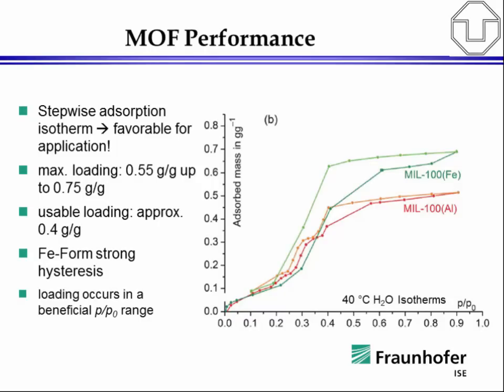Here it is really the tunability. Metal organic frameworks can be tuned in terms of hydrophobicity, hydrophilicity, that is the water uptake and at which relative humidity the water uptake starts can be tuned. And you can see this here for an aluminum-based MIL and for an iron-based MIL. They have both very high adsorbed mass and water uptake, here almost 78%, so very high water uptake, but it is also possible to tune the hydrophobicity.